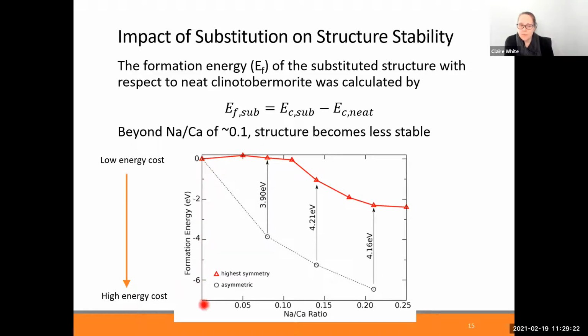But as this becomes more negative, the way that we've defined this formation energy means there is a higher energy penalty for having sodium in your structure compared to calcium. What's shown on the x-axis here is the different levels of substitution of sodium: small levels on the left, high levels on the right. It's interesting to see there's a cutoff point whereby if you have a small amount of sodium in your structure, the structure tends to be as stable, looking at ground state energy, compared with the original clinotobermorite. But once you go past about 0.1 in terms of incorporation of sodium for calcium in the structure, you're losing this stability. It's becoming less favorable compared to the clinotobermorite.